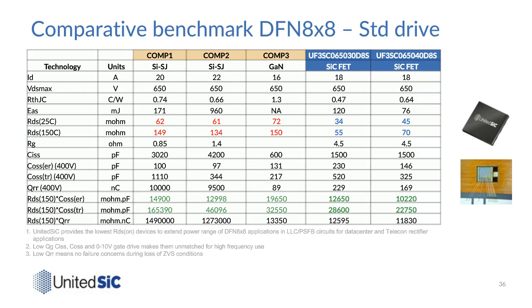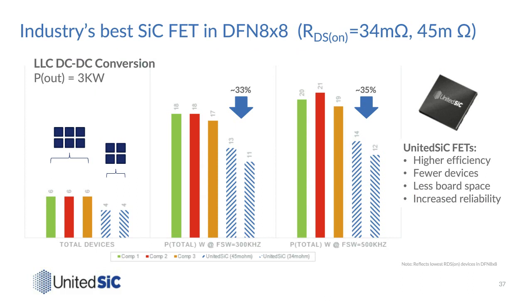If you wanted to build, for example, an LLC converter where you were using these DFN devices, in a situation where there's very little room to dissipate power, you can actually swap 6 competitive devices for 4 of ours. You end up driving down the losses. Even up to 500 kilohertz, you can use these devices, 4 swap for 6, and also drive down the power losses. So you get fewer devices that take up less board space. You're running at higher efficiency, and you're basically dissipating less energy.